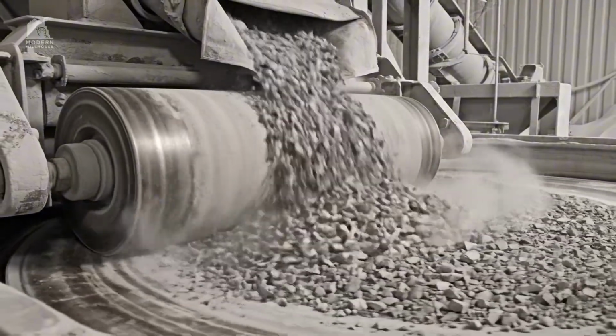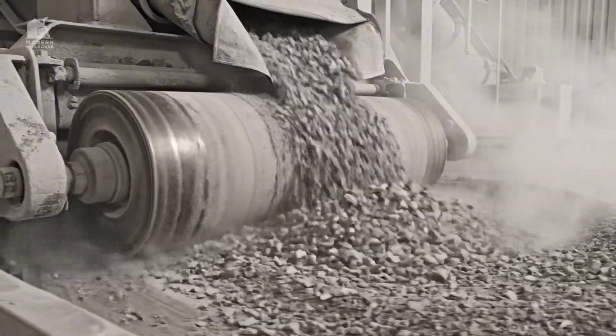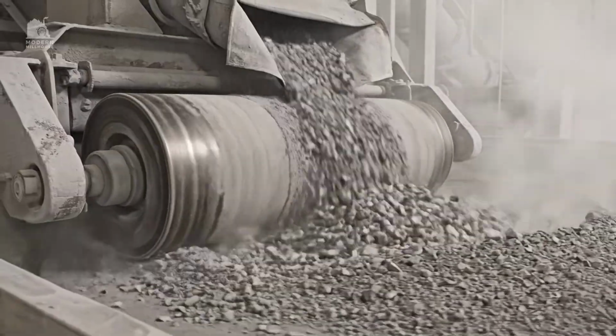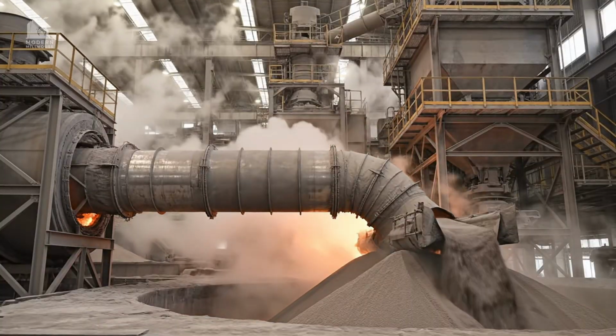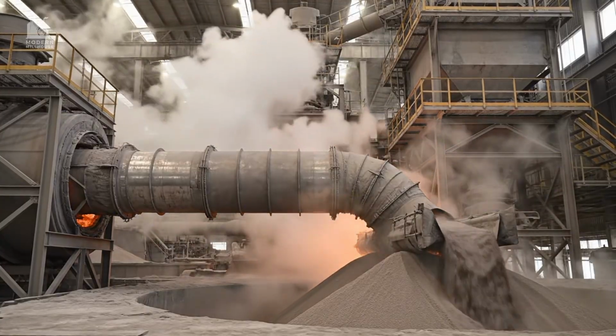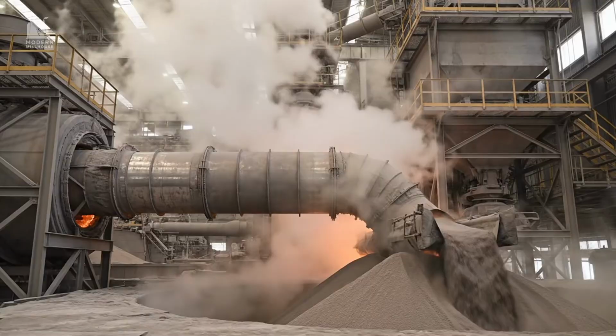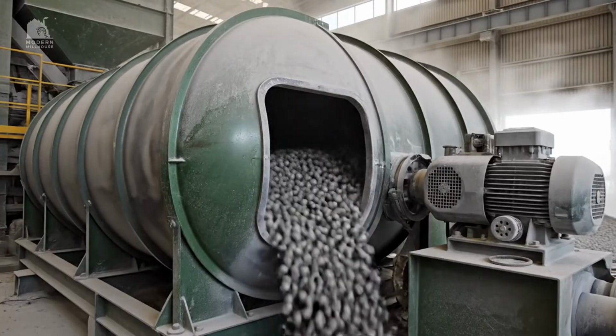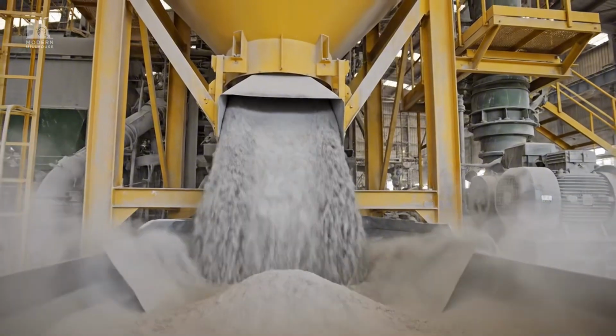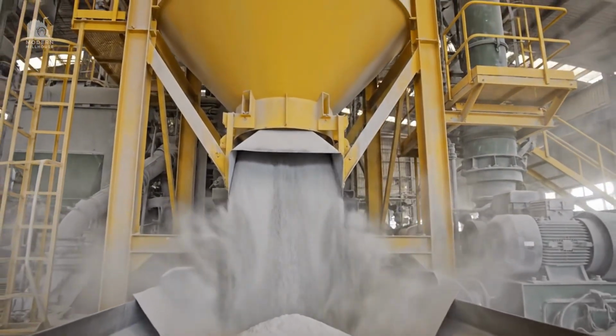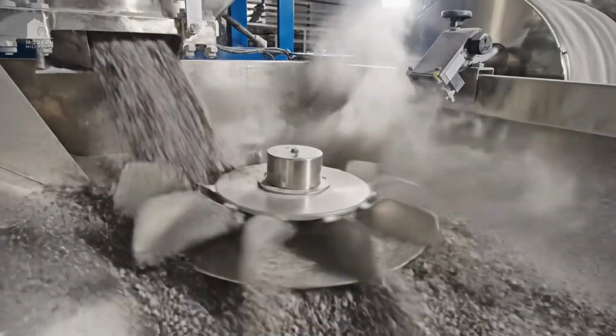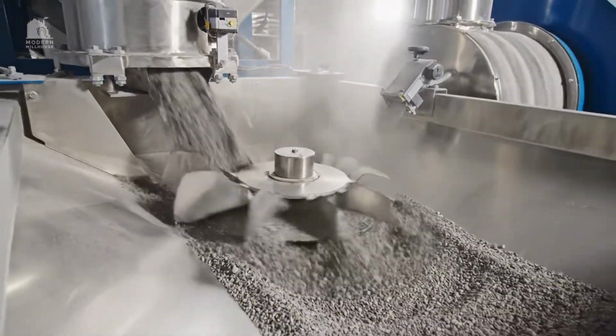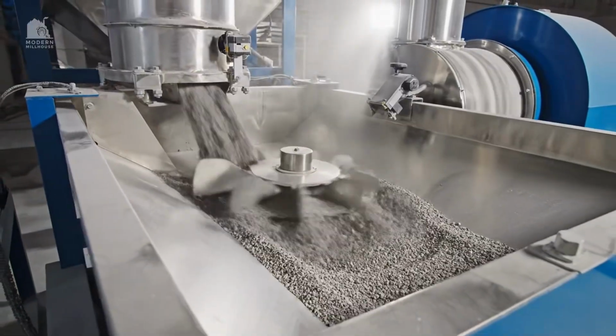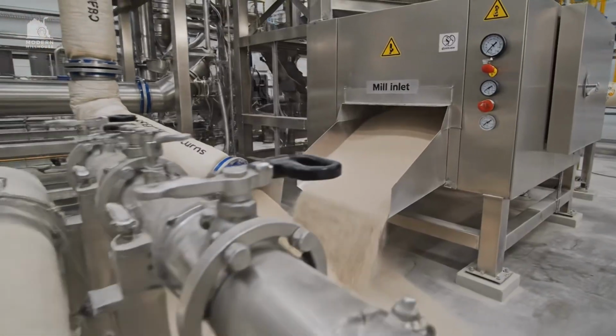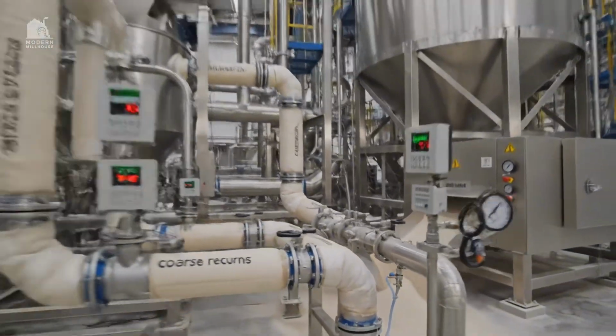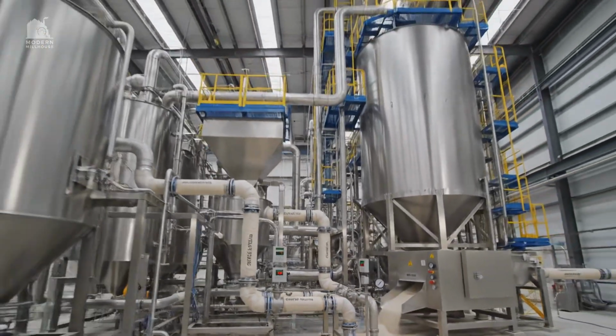Grinding reduces particle size and exposes fresh surfaces, making later calcination and clinker formation more efficient. In the dry process, kiln exhaust heat is reused to dry the raw materials as they are ground. Some plants use ball mills, but the goal remains the same: produce consistent raw meal with controlled fineness. The separator classifies particles, sending fine material forward and returning coarse material for more grinding. This closed loop stabilizes quality because the system self-corrects until the product meets the target size.